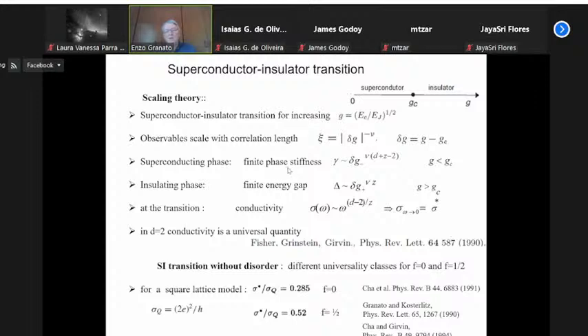And this phase stiffness, from scaling theory, scales with the correlation length, and you can show that it vanishes as you approach the transition. Delta g here is the distance to the critical point. It vanishes as a power of the distance to the critical coupling of the superconductor-insulator transition, with an exponent which depends on the correlation length exponent and the dynamic exponent z. In the insulating phase, the energy gap for the insulator has this dependence on the distance to the critical point, and it vanishes as you approach the transition point from above.